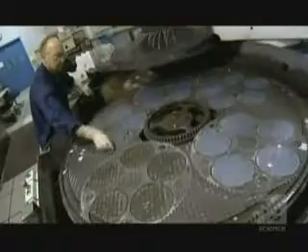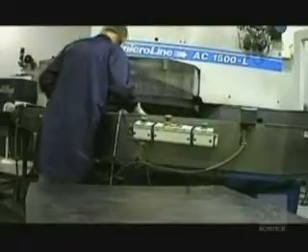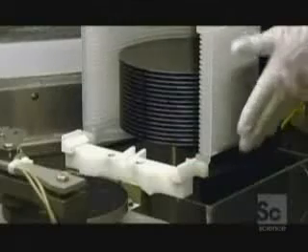After testing with chemicals and x-rays to check its purity and molecular orientation, it's fed to a silicon salami slicer. This 10-ton wire saw uses a fast-moving web of ultra-thin wire to produce wafers of silicon that are just two-thirds of a millimeter thick and 99.999% pure. Once cut, there are microscopic marks left on the wafer's surface, so it's buffed using a process called lapping. After a twirl in a high-powered polisher, they are still not smooth enough, so they're given yet another buff using a chemical process. The result is wafers with a surface roughness of less than one-millionth of a millimeter — buffed to a sheen and finally ready for etching with the circuit design.